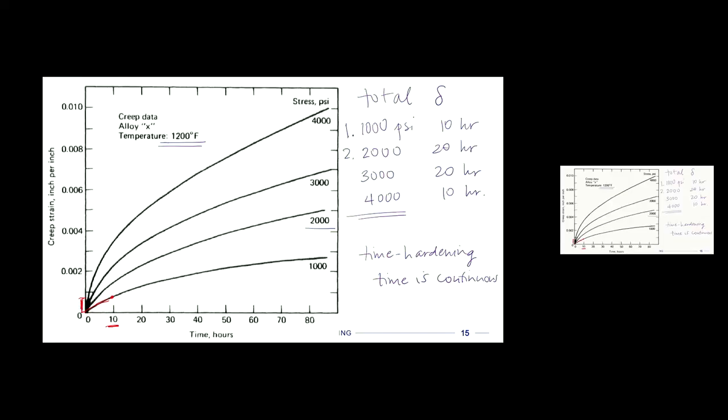I'll just draw it as like a red bar here for that first phase. So it's pretty straightforward. It's close to half the mark up to 0.002, so I called it 0.0008, right? Or 0.08%. 0.0008. So for the first phase, that's what we got.